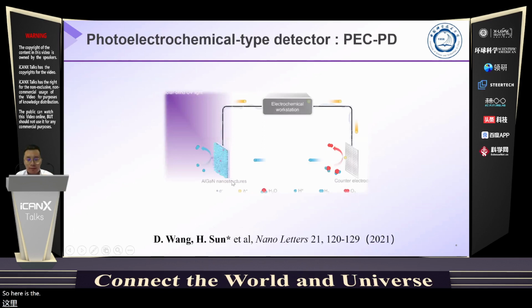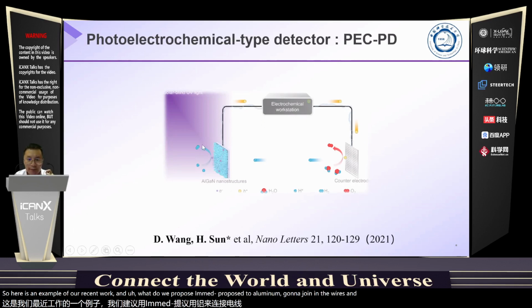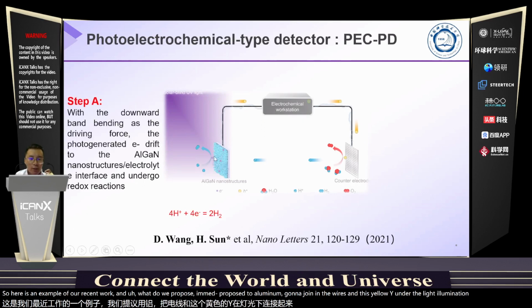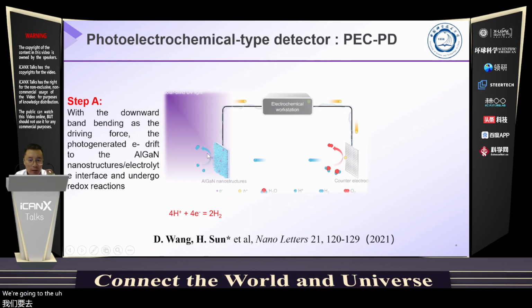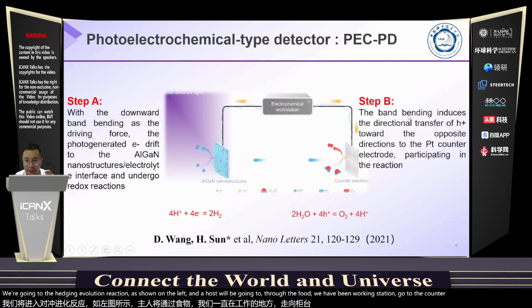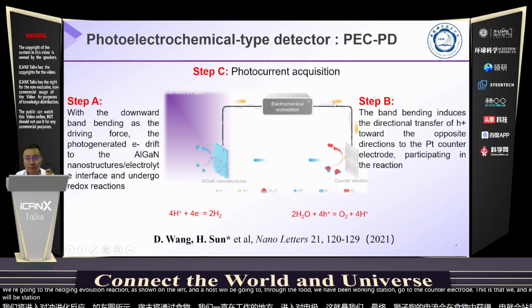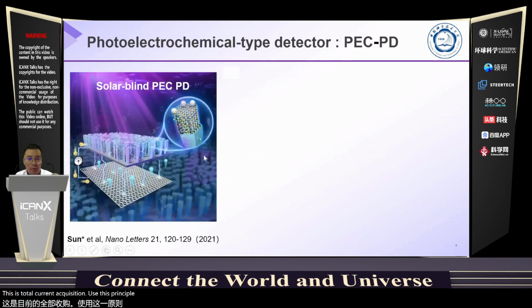So here is an example of our recent work. We propose to use aluminum gallium nitride nanowires. Under light illumination, these nanowires generate electron-hole pairs. Electrons go into the hydrogen evolution reaction as shown on the left, and the holes go through the photoelectrochemical working station to the counter electrode. This is step B, and eventually the photocurrent is acquired in the photoelectrochemical working station. This is photocurrent acquisition.